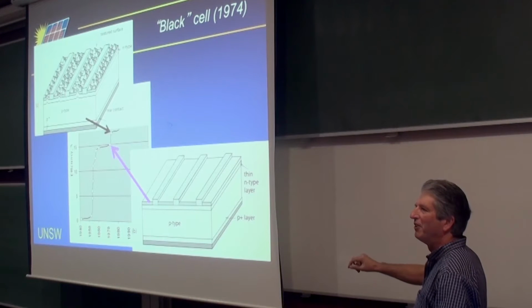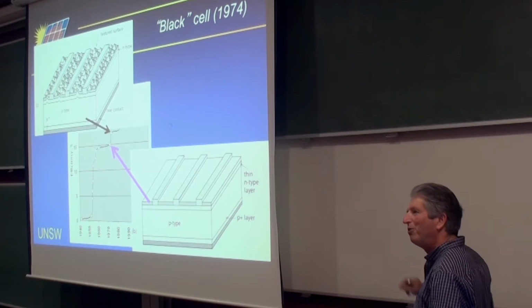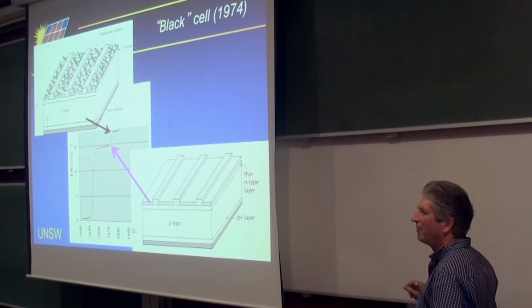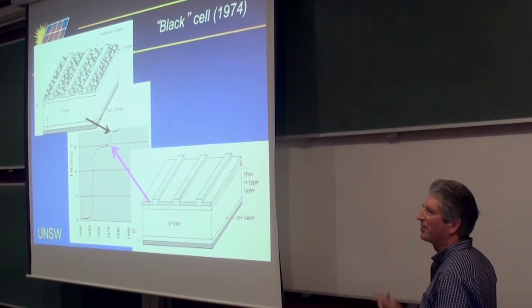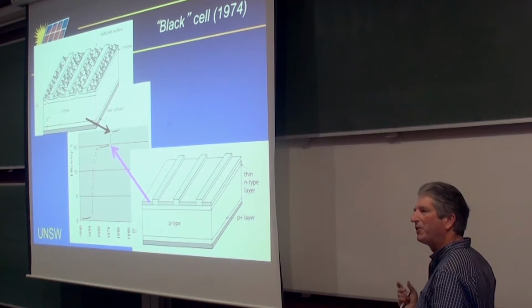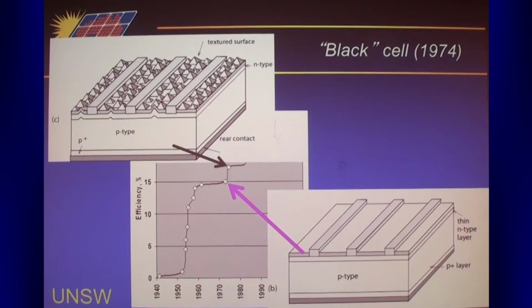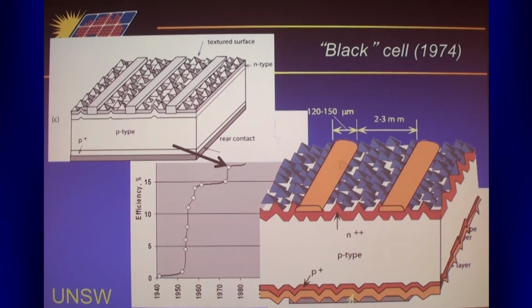And if you think about it, if you've got 10% reflection on your first loss, if you have 2 bounces, you get 10% of 10% loss after the second bounce. So you can reduce a cell with 10% reflection down to a cell with 1% reflection by that technique. So it's a very good technique for getting very broadband anti-reflection properties. And it's used in most commercial cells.